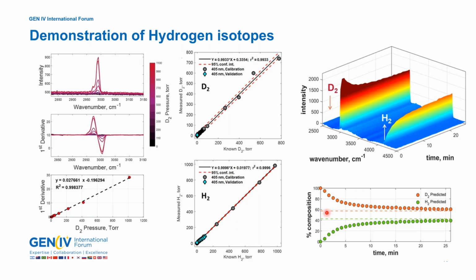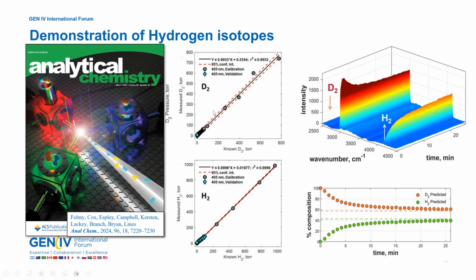And at the end of the experiment, the dotted lines here are the measured values using our mass spec, which was also associated with the gas manifold line. We can measure the concentration by mass spec, and we measure exactly what we see with the mass spec. And this work just recently, in this last month, appeared in Analytical Chemistry with the reference right here.